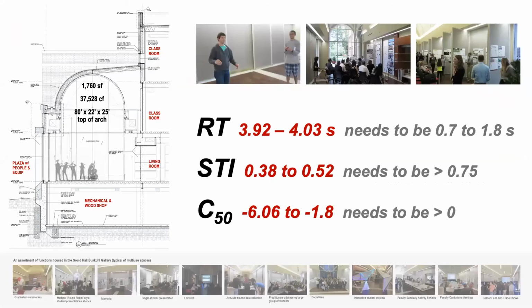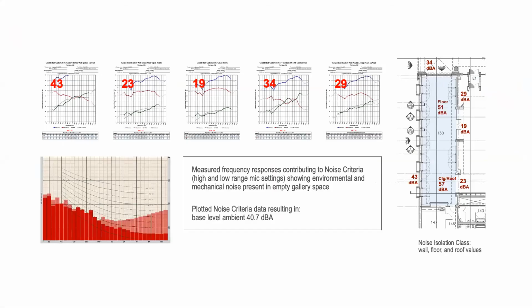Occupants report discomfort and confusion related to acoustical issues in the space, primarily a lack of comprehension based on the acoustically reflective materials and spatial volume, producing high RT, low STI, and low C50. The measurements also demonstrated low noise isolation class or NIC values, which are similar to a field or apparent STC test for wall and floor assemblies, also causing noise criteria NC to exceed published recommended limits.